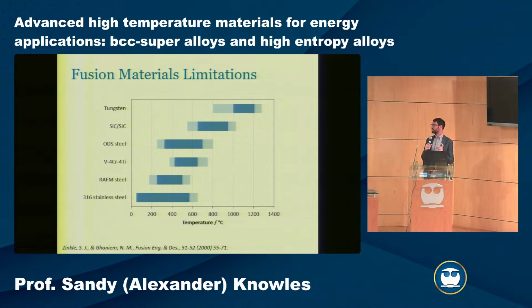And all these materials have a bit of a temperature window by which we can use them. So at high temperature, things become soft, or you get creep processes. At low temperature, you get irradiation and embrittlement. So if you irradiate a material, you damage the lattice, and that can lead to embrittlement of the material. So you increase the strength, but reduce the ductility.